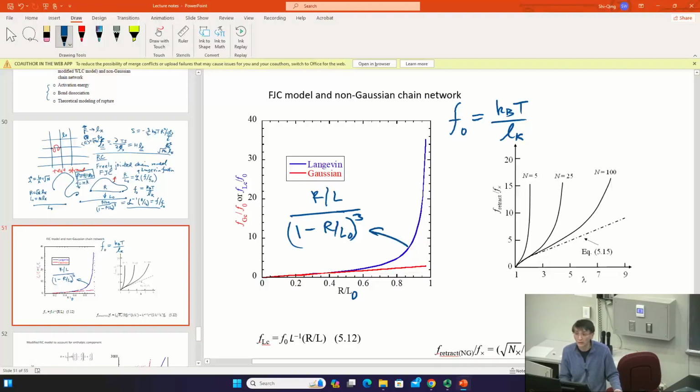We do that a lot for the rest of our few weeks. Kuhn length characteristically is generally, you may just treat it as something on the order of 1 nanometer. It's true for many of the linear flexible polymers. At room temperature, you know the value of kT. So F typically is something around 4 piconewton.